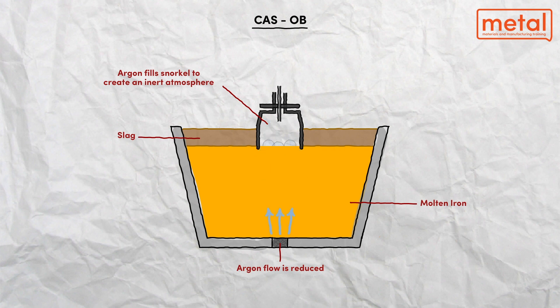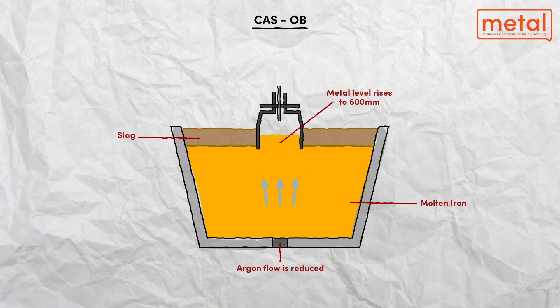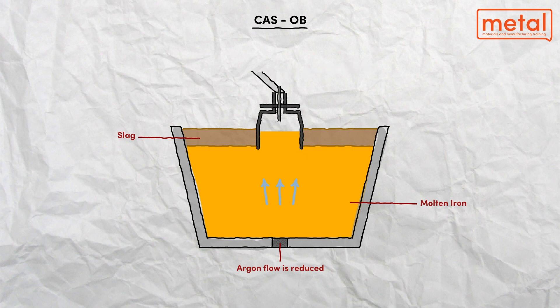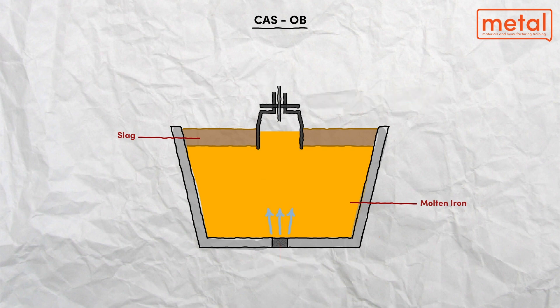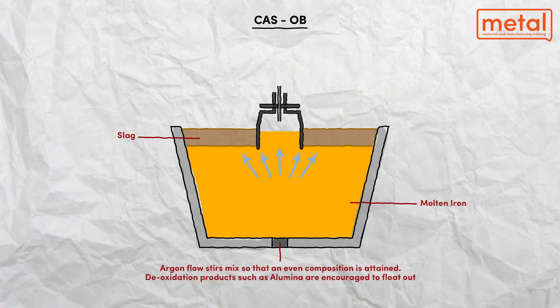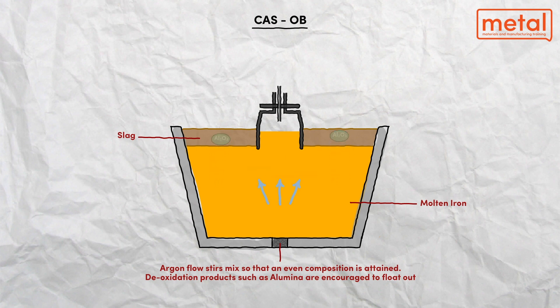The lower end of the bell is immersed into the liquid steel in the area of the open eye by at least 200 millimetres. After having lowered the bell in the liquid steel to the desired depth, the flow of argon is reduced. The temperature of the liquid steel and the activity of dissolved oxygen in it are measured. The free surface of the liquid steel from the slag inside the bell serves as the place for addition of granular aluminium and other additives for deoxidation.